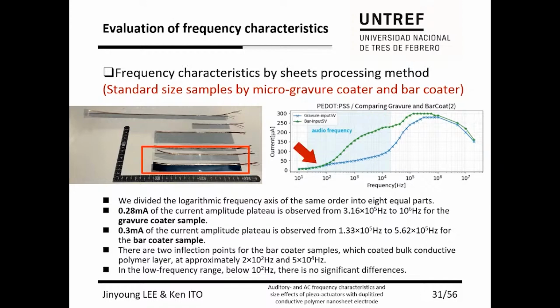At the low frequency that corresponds to the vowel range, we couldn't see significant enhancement, even when we changed the thickness of conductive polymer. In general, consonants are important to transmit the meaning, and vowels convey speaker's identification, gender, age, and emotion, etc. We examined characteristics in the low frequency range by changing size of the actuator to strengthen vowel transmission.